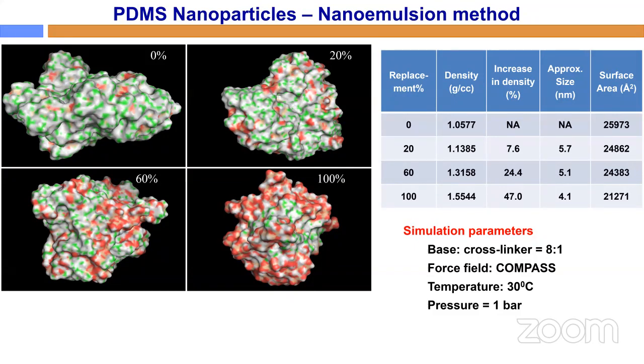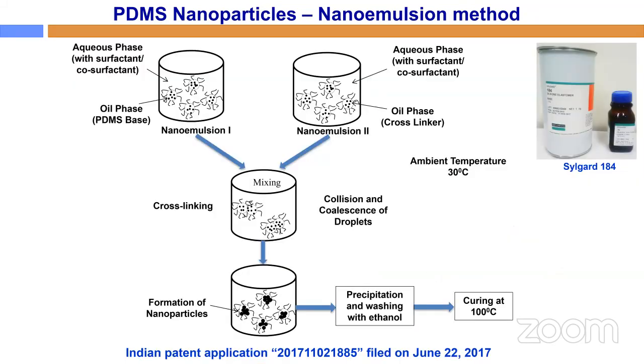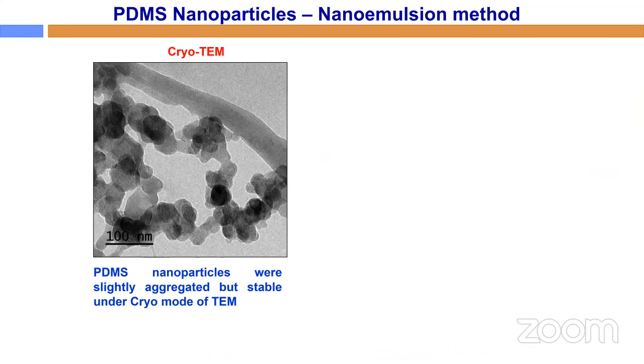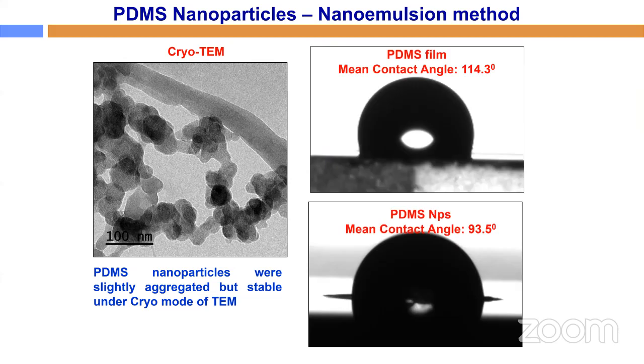So what we thought is that if we have a hydroxyl group present on the PDMS, it will not form as a particle, it will form as a thin film. So we used the same technique. After the nanoparticle is formed, we treated it with sodium hydroxide addition. That will hydrolyze the silica, the SiO, which introduces a lot of OH groups. After that, the nanoparticles are stable, and then we measured the contact angle.